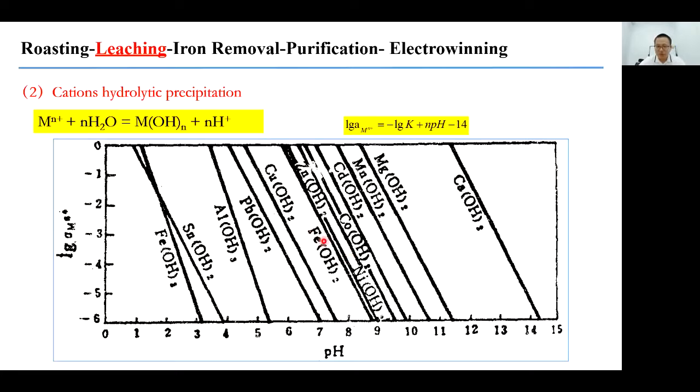Once we cross a pH value of 7, it starts to precipitate. So iron should stay in the ferric or trivalent state, which benefits the separation. So we use some oxidation reagent in the leaching part to oxidize iron to ferric and get it precipitated in the residue.